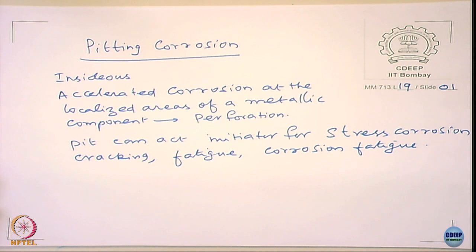You know the reason? Because when you have a pit which is very localized, it can be a stress riser. The stress intensity at that location can be quite high, and so the crack can initiate and grow even below the yield point of a metal. So, a pit is in fact very detrimental, and can bring down the component life quite significantly, leading to premature failures.